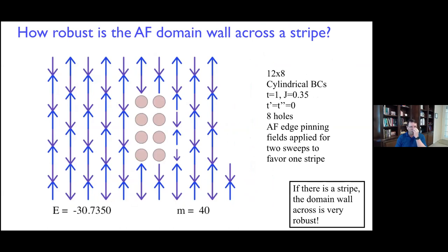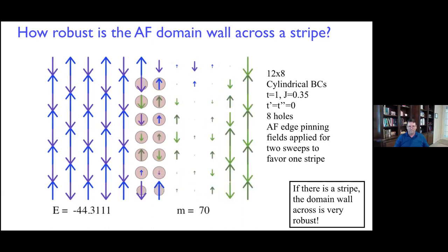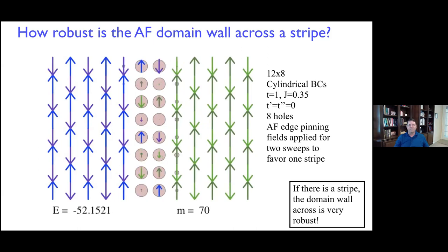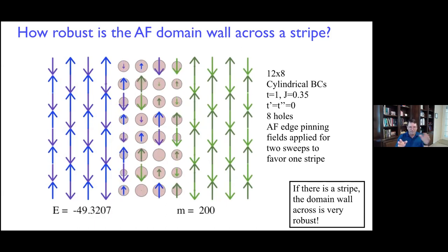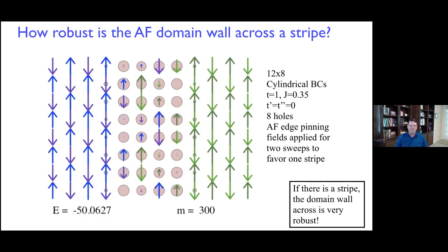This is an experiment where we try to see how robust the domain wall nature of the antiferromagnetism is across the stripe. To do this experiment, I temporarily put a pinning field on the two sides of the system that forces them to be in opposite domains, because it wants to split into two stripes. That sets up a regime favoring one stripe. Now I turn off the edge fields that are forcing it, and it's back to the free Hamiltonian that can do what it wants.